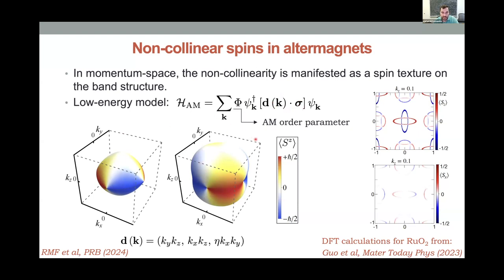And what you see generically here is that when I have a Fermi surface, I have a metal, the Fermi surface splits in two, except along just a handful of points. These are the pinch points. And overall, they're going to have a spin texture. Unless I'm looking just in one plane, in this case k is equal 0, there will be other components. And indeed, these are DFT calculations with ruthenium oxide in this paper.